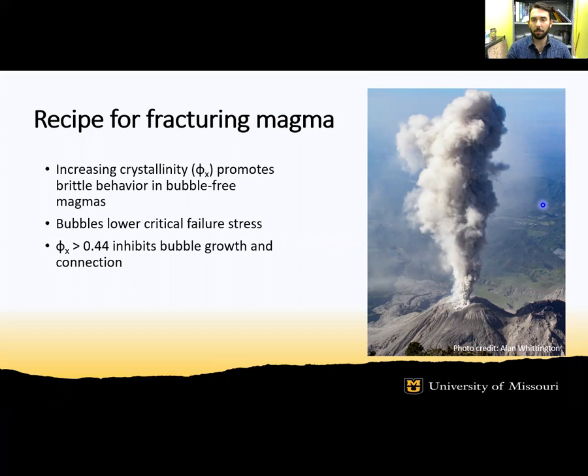With this in mind, tests by Cordonnier, Pistoni, and others showed that increasing crystal content does promote brittle behavior, and the addition of bubbles exacerbates this effect further. However, there is a crystallinity threshold above which bubble growth and connection are impeded. This promotes gas storage or bubble entrapment in more crystalline magmas. Consequently, the failure stress is increased if bubbles remain trapped within the crystal framework. Crystals, therefore, can aid or hinder gas escape, thereby playing a crucial role in controlling eruptive behavior.